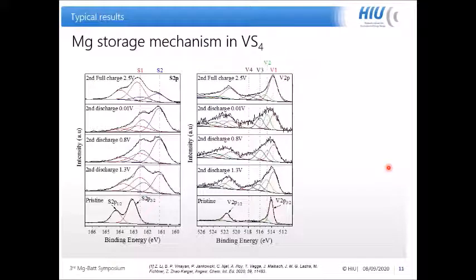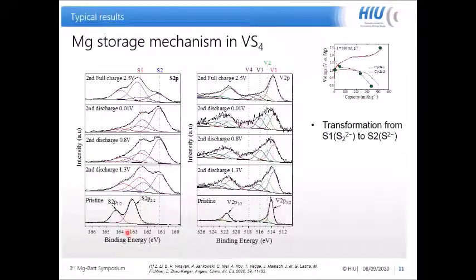Then we further studied the magnesium storage mechanism in the VS4 cathode. We used XPS spectra to track the change of the oxidation states of vanadium and sulfur. We took the electrode at the pristine state, at discharge to 1.3 V and 0.8 V, and at the fully discharged and fully charged states. In the sulfur spectrum, we see that during magnesium insertion, the peak shifts from the original state, the red one, to the blue one, or let's say we have a new doublet formation during the insertion of magnesium. This indicates a transformation from disulfide to sulfide.